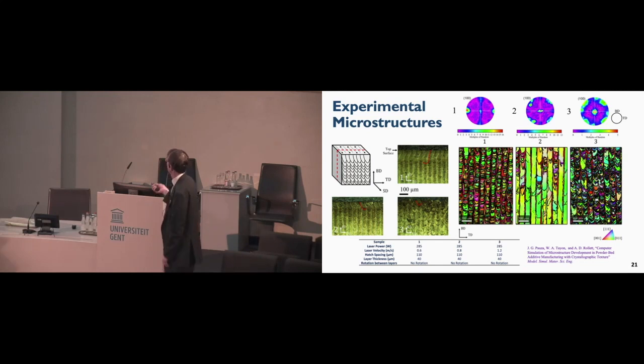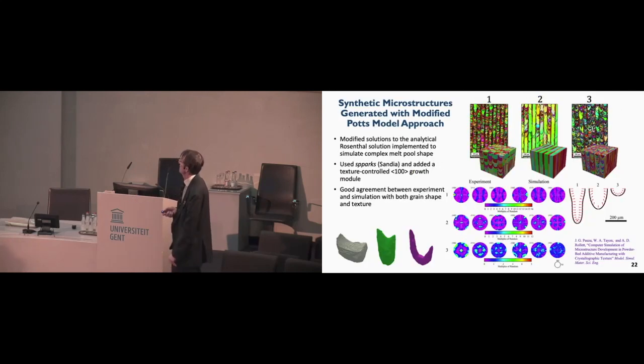So my student at the time, Joe Powers, set about modifying a code called SPPARKS. Now SPPARKS is a kinetic Monte Carlo code, or Potts model, and the nice thing about it is that for 3D simulations, it's relatively efficient, and it's publicly supported. We simply added texture to it, so as to actually simulate that 100 preferred growth orientation. And so with a certain amount of work, that panel of three EBSD scans shows you the experimental microstructures, and these are the results of the corresponding simulations.